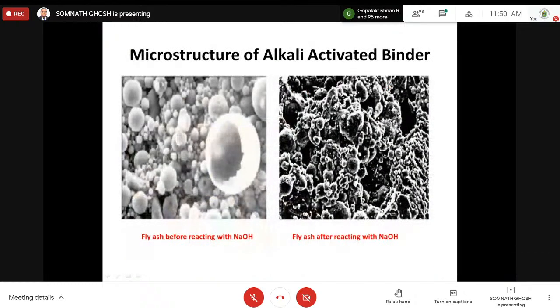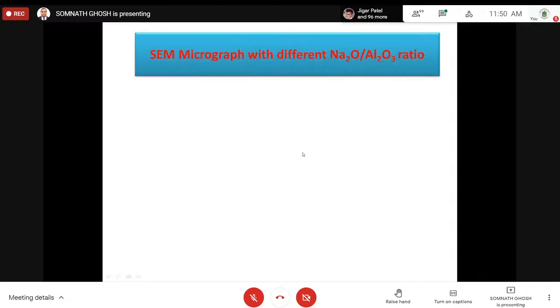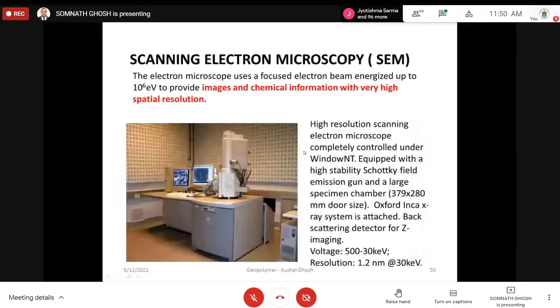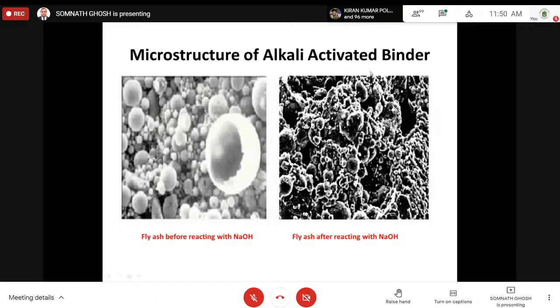Now just see the microstructure of alkali activated binder. See, fly ash before reacting with sodium hydroxide, it is like this. The moment it is reacted with sodium hydroxide, it becomes so dense. After formation of gel and all, it becomes so dense, right? These things, you can only understand through this scanning electron microscope. Otherwise, you will not be able to understand the microstructure.